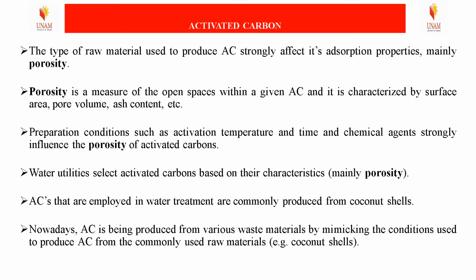Porosity is a measure of the open spaces within the AC, and this is characterized by surface area, that is BET, pore volume, ash content, and many physical properties can be studied. Preparation conditions such as activation temperature and time and chemical agents strongly influence the porosity of activated carbons. Water utilities select activated carbons based on their characteristics, mainly depending on the porosity.